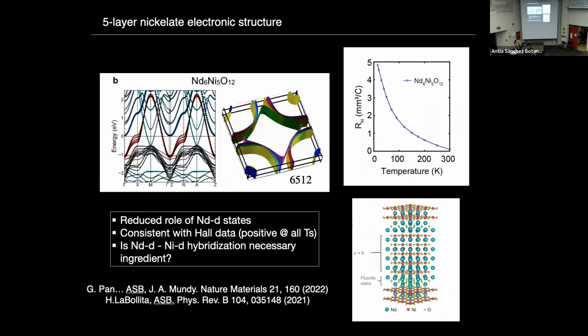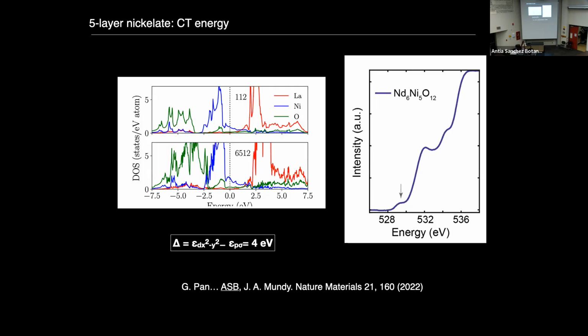So basically this tells us, or at least that's our perspective, that perhaps nickel d and neodymium d hybridization is indeed not a required ingredient for superconductivity in these systems. Moving on to the degree of p-d hybridization or charge transfer energy, we get here a smaller value. Remember, for the infinite layer compound, it was 4.4. Now you go down to 4 eV. Once again, this is consistent with the appearance of a pre-peak at the oxygen K edge in the X-ray absorption.